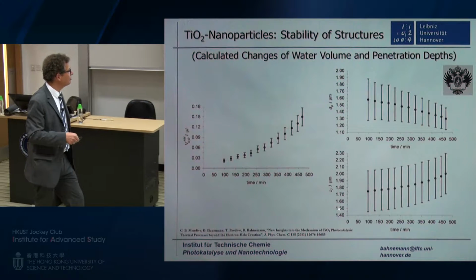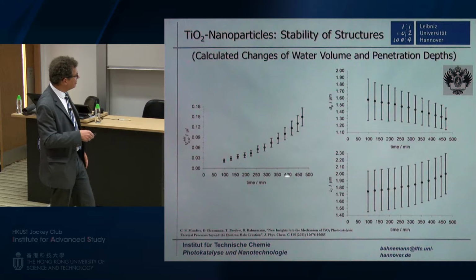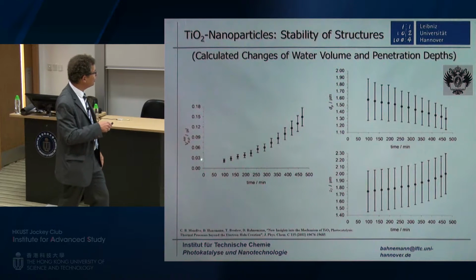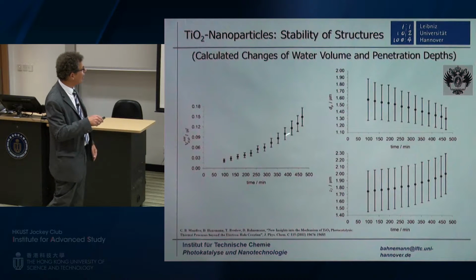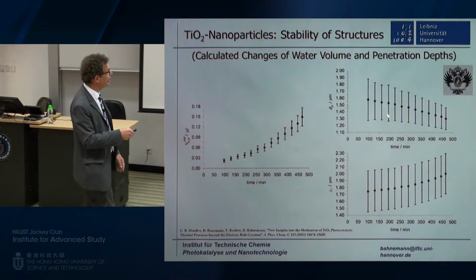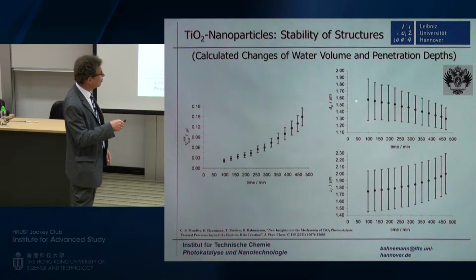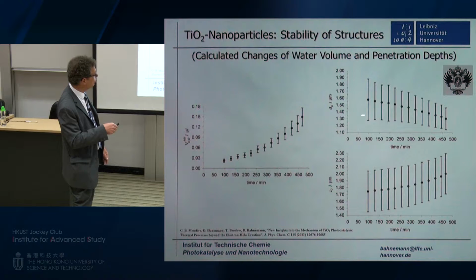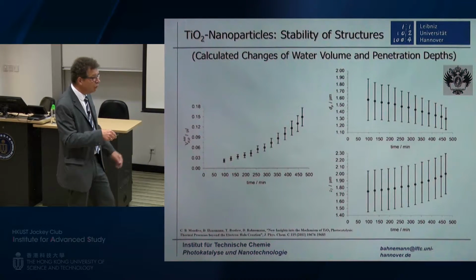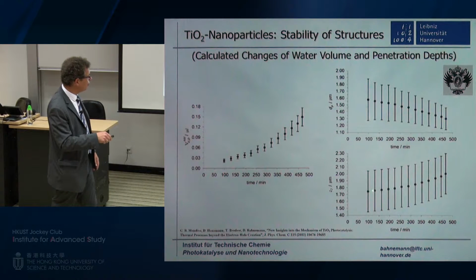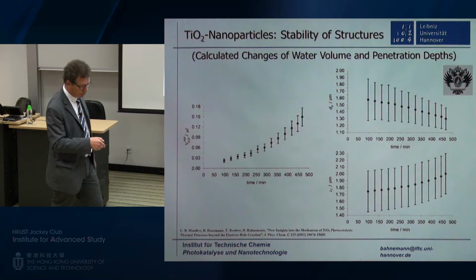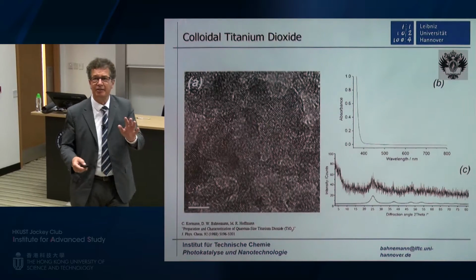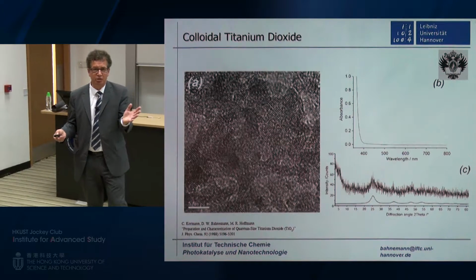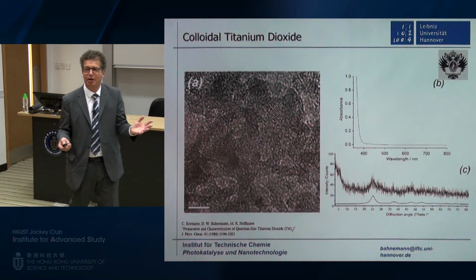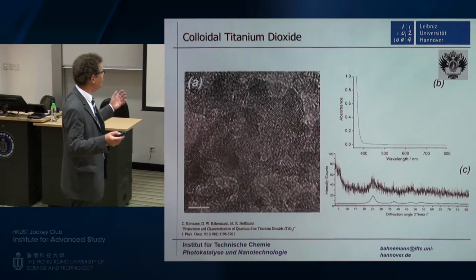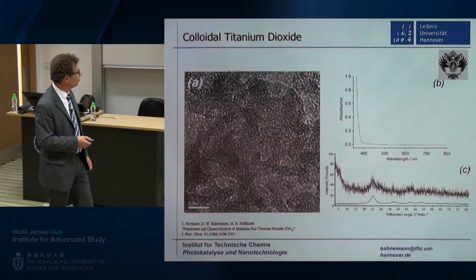These are the results of the calculations here: this is illumination time, and this is the volume of water. So we are talking about 0.1 microliters, 0.15 microliters of water additionally intercalated in the system, which means your probed water layer goes down from initially 1.6 micrometers to about 1.4 micrometers, while the probed TiO2 layer with the water inside goes up from about 1.7 micrometers to about 1.9 micrometers. So this could explain what we see in this blank experiment. I'm sure there could be other explanations, but so far we didn't come up with any other. And I have also not seen other people trying to explain what we have been observing.